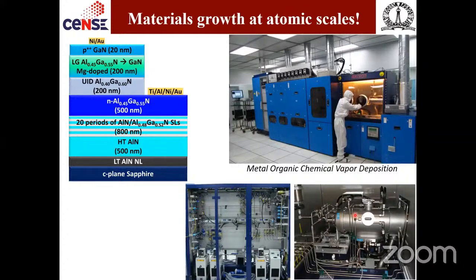What I would like to highlight here is that the gases we have to deal with in such reactions are extremely pyrophoric and toxic. So if there is a leak, the body would not know whether to die of the toxicity or of the fire that is produced when these gases are exposed to the environment. It's very dangerous if we have a leak, and that's why we have a series of leak detectors hooked up to the reactor. If these detect any leak, it shuts down all the gas lines in a fraction of a second, and that's how you can do such experiments in a safe manner. But it's a very harmful set of gases that we have to deal with to synthesize these semiconductors.